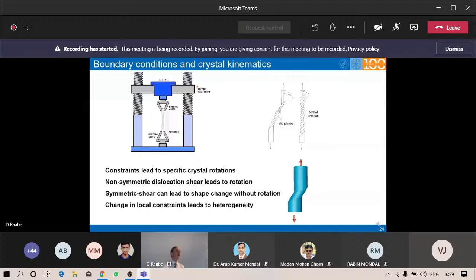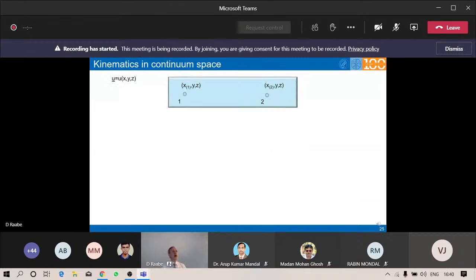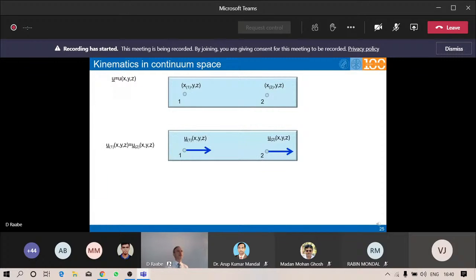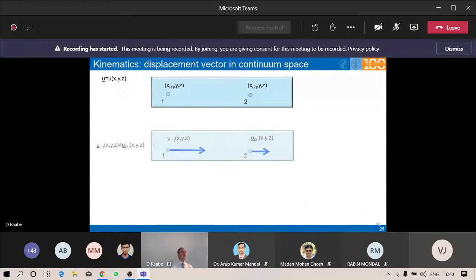Now we always have to translate these crystal kinematical aspects into continuum space. And here you have our formal description of two coordinates, which are both shifted as indicated by these blue arrows by a displacement vector u1 and u2. In this case, the displacements that describe the distortion that you impose on this block, on this continuum, are identical. And when these two points represent that block of material, that means you are just shifting this continuum from left to the right. When you repeat that thought experiment, but you impose two displacement vectors, here shown in blue, which are not identical, either in magnitude and or direction, then you impose a distortion. That means these are not compatible.